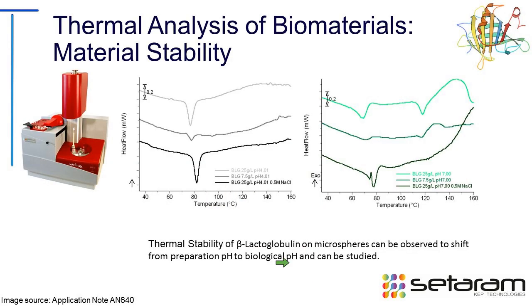So a good demonstration of this application is with calorimetry, looking at the stability of this little protein up here, which is beta-lactoglobulin, which we've appended onto microspheres. So what you see here is the thermal stability of just a DSC run of a protein appended onto these little microspheres, and we can see the protein unfolding here at around 80 degrees. Well, it's degrading and coming off. What's important here is that this